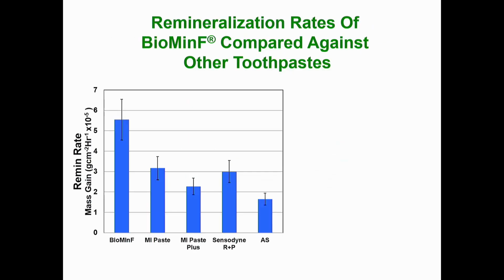And we measure the rate of remineralization that occurs. The next slide shows the data. The block on the far right is labelled AS, which is artificial saliva. When you immerse the enamel blocks in artificial saliva, you get a remineralization effect. The next one is Sensodyne Repair and Protect, which does about twice what artificial saliva alone does.